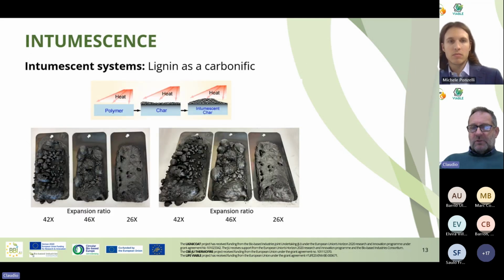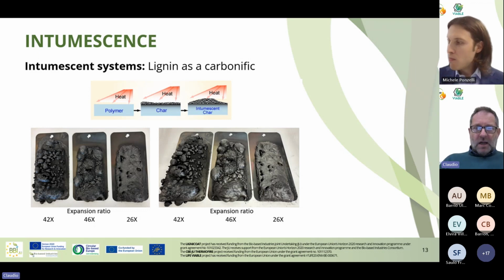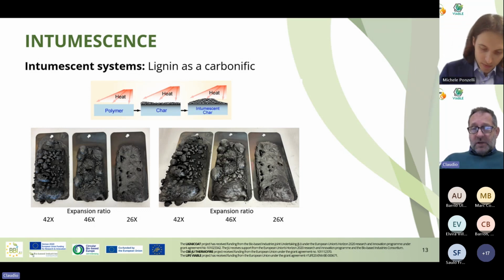But this is not the most difficult thing to achieve, because we need to have also another material that is able to pass the test for floors and also for walls and ceilings. And we believe you normally need an intumescent system to do that. Aitor explained what an intumescent system is, what components are needed. And here comes another idea. A carbonific, what Aitor called the carbon source, is normally a material rich in hydroxyl groups. The most common is pentaerythritol, but also starch or sugars have been proposed in literature. And lignin has a lot of hydroxyl groups. So can it work as a carbonific, as a carbon source?